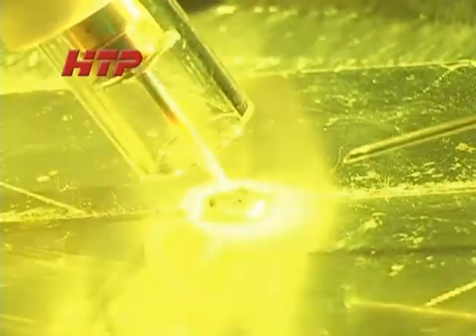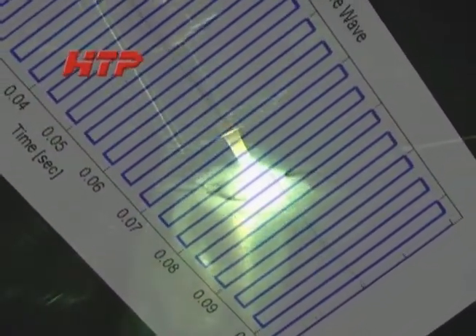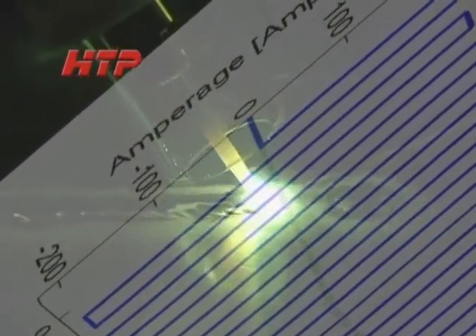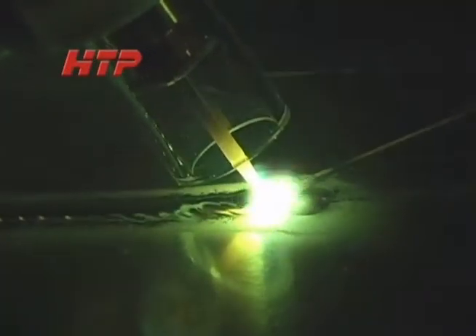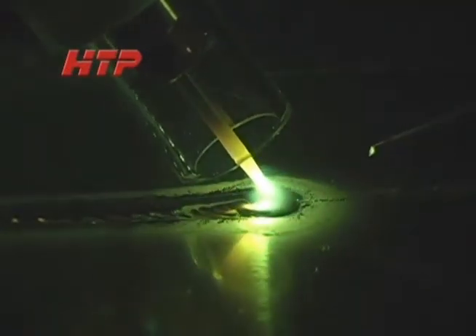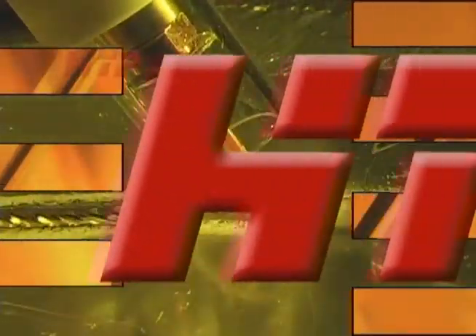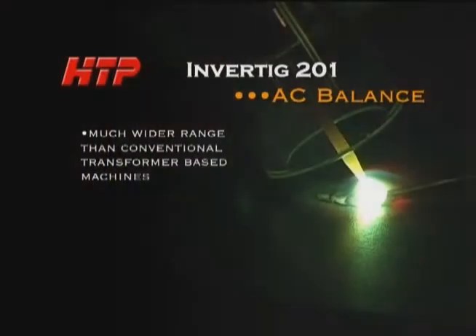The AC wave of the 201 passes through the 0 point so fast that high frequency is only used to start the arc and not necessary to reinitiate it. This minimizes HF interference. In fact, it is possible to do touch start welding in the AC mode. And the InverTIG 201 allows you to adjust the AC balance over a much wider range than conventional transformer-based machines, from 10 to 90%.